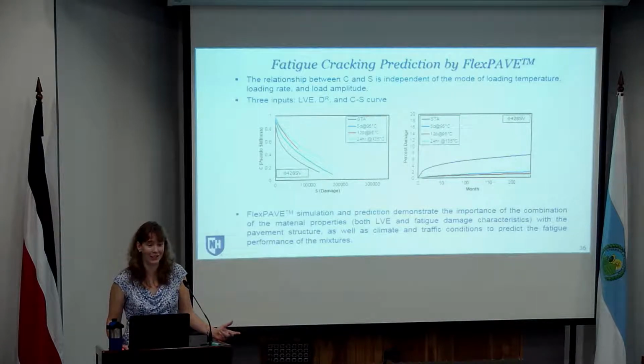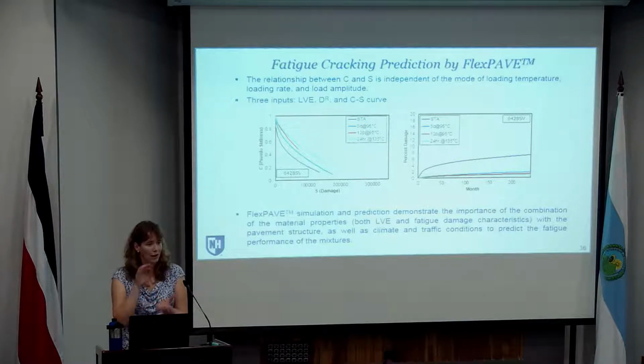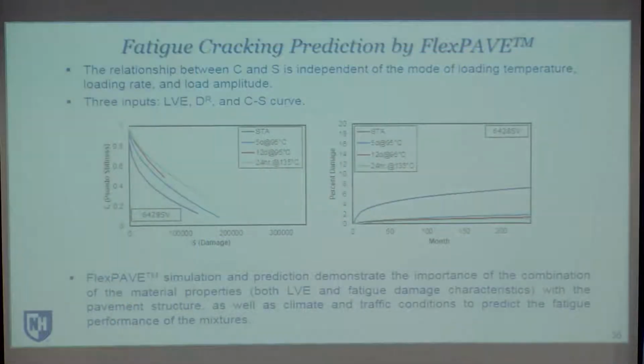Seems to not make sense really initially, right? But then if you think about what's happening as the materials are aging, if you're looking at the same pavement structure, you've got a stiffer material, so you've got a lower strain response, and if that strain response is lower than that fracture, you're going to get a lower amount of damage, right? So it's that combination of your fracture properties, your viscoelastic response, and that pavement structure that you put it in. So if we do a different pavement structure, use a different traffic loading, these things can change. So again, just something to remember when you're looking at fatigue, you've got to consider all of it.